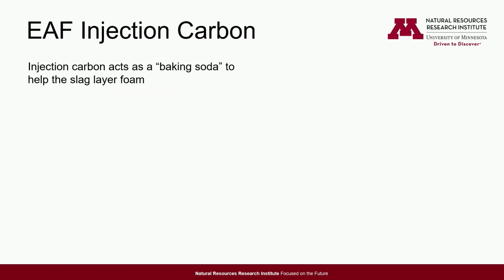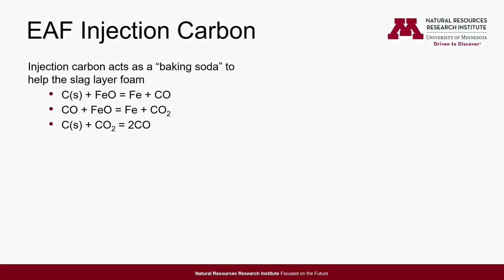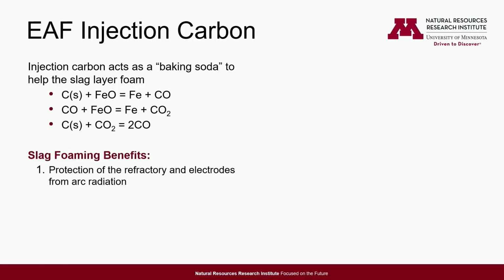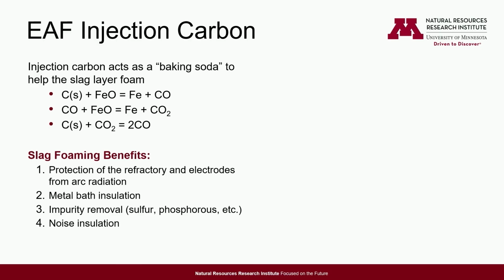So injection carbon acts as a baking soda to help the slag layer foam. You can see the reactions here. What are the benefits of slag foaming? One, it helps protect the refractory electrodes. It helps with metal bath insulation. It also helps with impurity removal. So we're helping remove the sulfur and phosphorus and other things that we don't want in the end iron. And then it also helps with noise insulation.